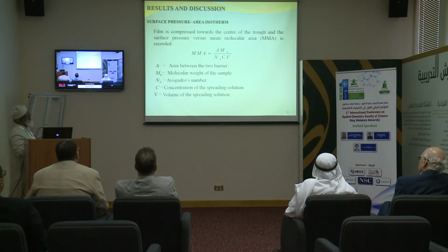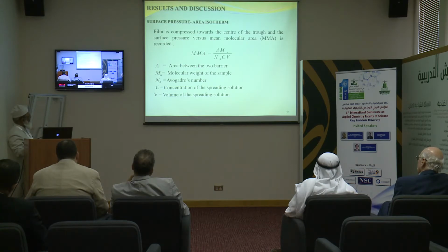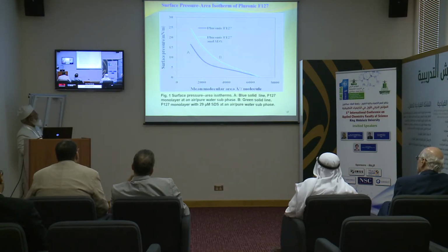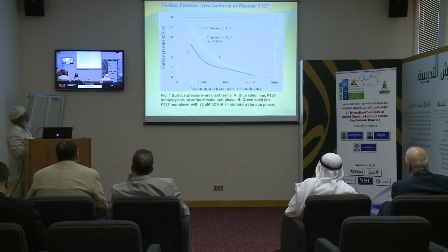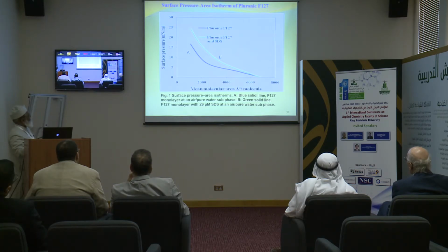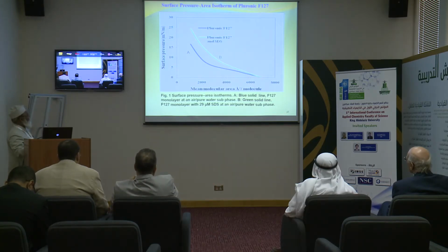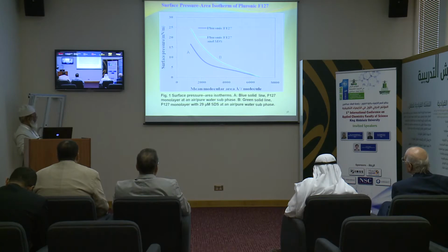The surface pressure is used for the preparation of the pi-A isotherm. The film is compressed towards the center of the trough, and the surface pressure versus mean molecular area was recorded, where the various terms have their usual significance. Now this is the comparison between the surface pressure area isotherm with and without the surfactant. The blue one, curve A, shows the variation of surface pressure with mean molecular area for the pluronic polymer, and the green one, curve B, shows the curve with the surfactant, that is the anionic surfactant SDS.